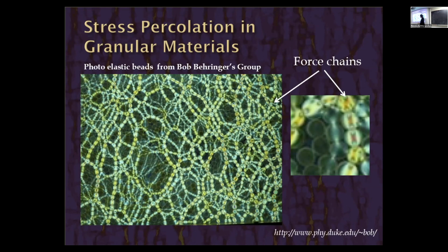These sort of semi-linear, more or less parallel to compression arrangements of grains are bearing the load, while other grains are doing absolutely nothing. You can see here, there are a bunch of grains, they're not lit up. Their experience of being loaded is just like oblivion. They don't know that they're being loaded, where their neighbors are carrying the whole load.